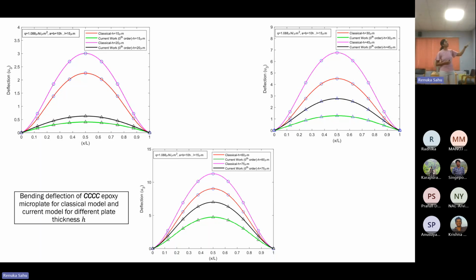The first graph considers 15 and 20 micrometers of plate thickness, and we have applied a distributed load on the plate. Here you can see the difference between the classical and the current work. As we move to higher thickness values of 30, 45, 60, and 75 micrometers, the difference reduces.